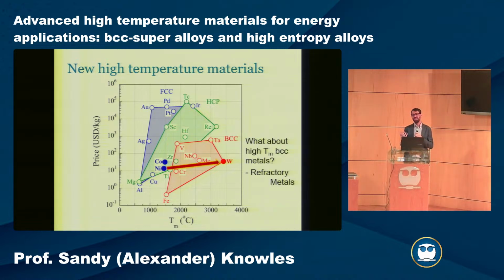So what else can we do? Rather than using an FCC-based material, we could go to BCC. So we could look at something like tungsten. Tungsten's got a 2,000 degree improvement of temperature above nickel, so nearly 3,500 degrees of melting temperature. But now we've switched from FCC to BCC. So we've gained on temperature. We actually still are quite accessible in terms of cost, but we've switched crystal system.